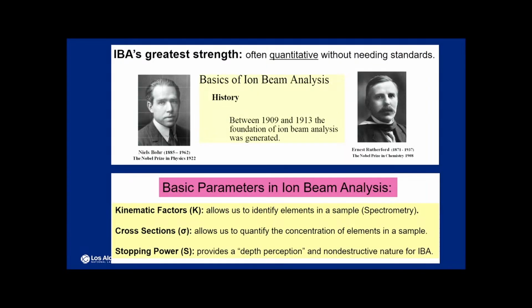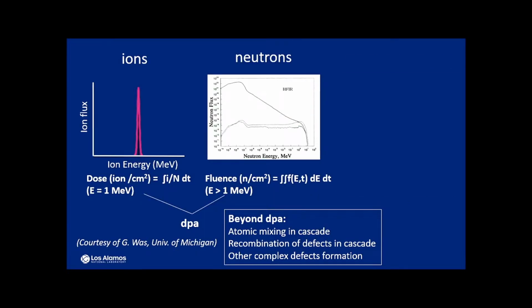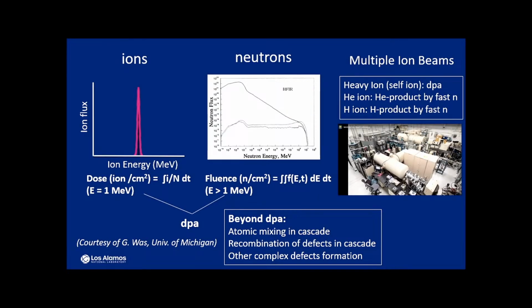I will show that. One of the strengths is that it is the most quantitative way, without the use of standards. You don't need sample preparation pretty much, because all the fundamental physics was solved a long time ago by those laureates. So, ions are not neutrons, obviously, so their spectrum is different. But we use DPA as a measure, again, as the commonality to try to merge them together.